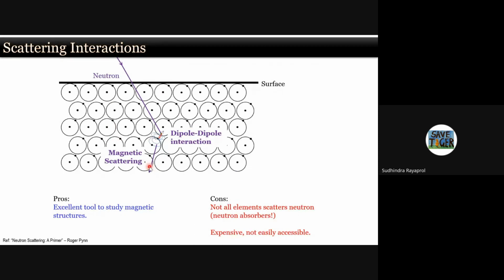It has a magnetic dipole. So the spin of the neutrons can interact with the spin of the unpaired electrons in your sample. Because of this dipole-dipole interaction, it can do magnetic scattering, right? So in addition to structural information, you can get magnetic structural information because of this magnetic interaction, which of course is an electron dependent one, but definitely it gives more information on the magnetic structure, which no other technique can give you.